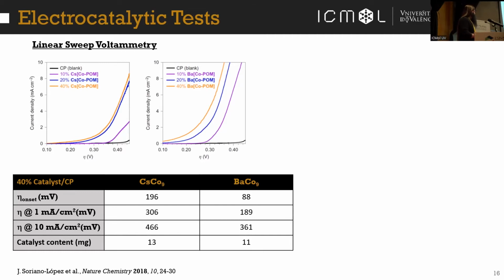We were very happy with that, but first we wanted to compare it with iridium oxide because it's basically the benchmark catalyst in acidic conditions. So we took commercial iridium oxide, we prepared the same carbon paste blends, and we compared the activity with this cobalt-9 polyoxometalate.